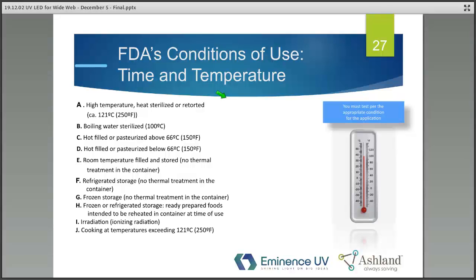Temperature is also critical for migration testing. The FDA has multiple conditions of use. You have conditions of use A through J. A is for high temperature retort. And as you go down, the conditions become a little less severe. Condition of use E is for room temperature. At that testing, you would test a product for 10 days at 40 degrees Celsius.